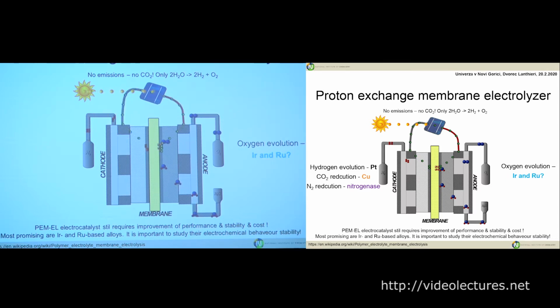So the catalyst. In this case, to split water to oxygen, you need iridium or ruthenium. Like platinum, it's very expensive and rare. On the other side, you should have platinum to make this hydrogen evolution, but you can also use something else. You can use copper, and then you can electro-reduce CO2 back to fuels. So this is using copper, and then ideally you could also reduce the nitrogen back to ammonia, and for this the only known catalyst that shows some activity is nitrogenase, which is an enzyme. But it's still super low efficiencies, but there is something there.